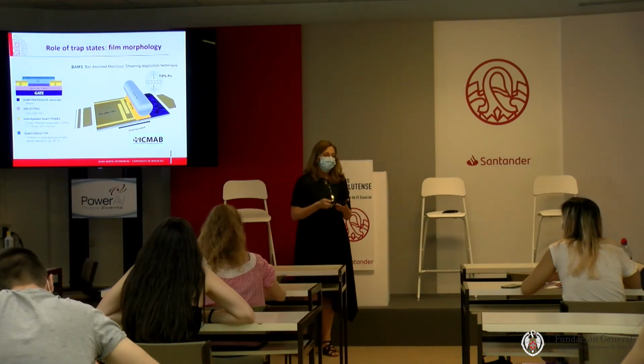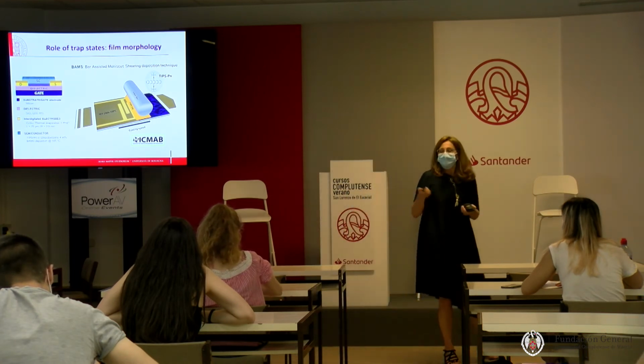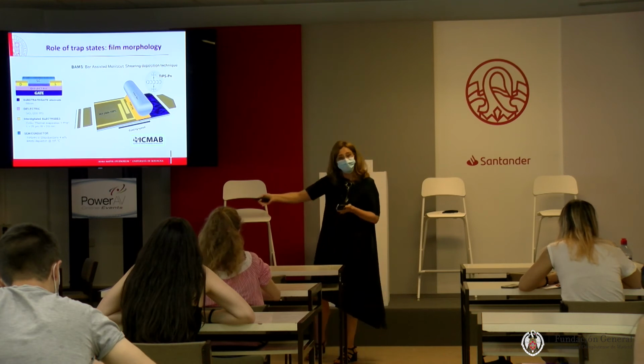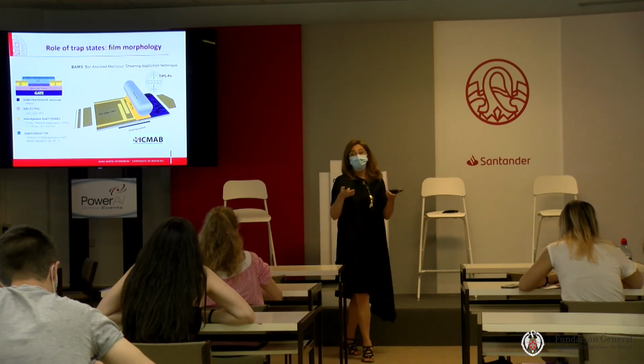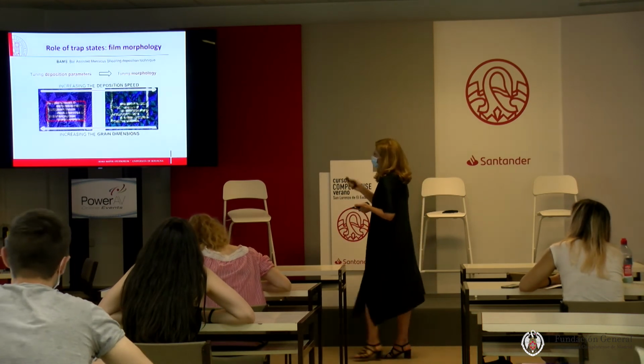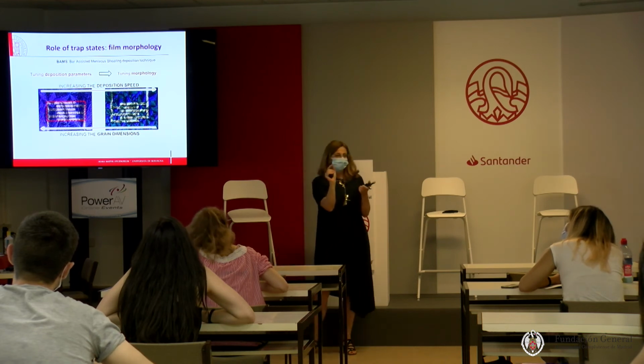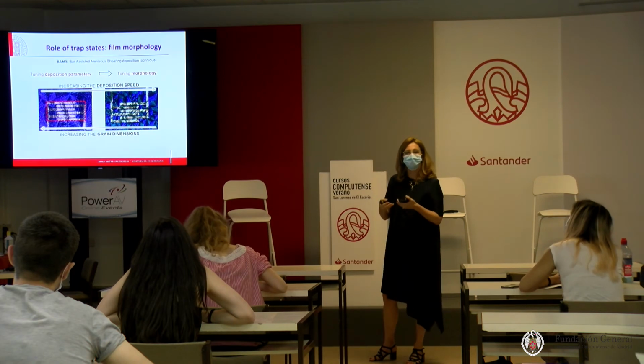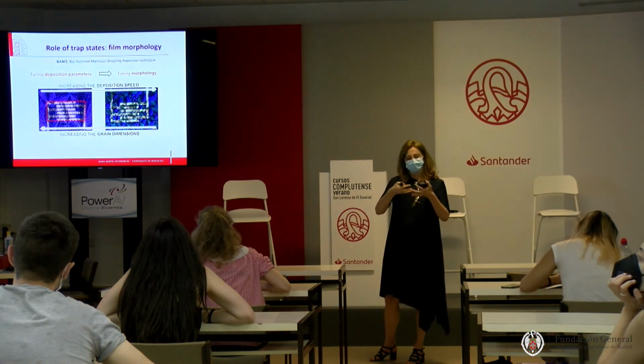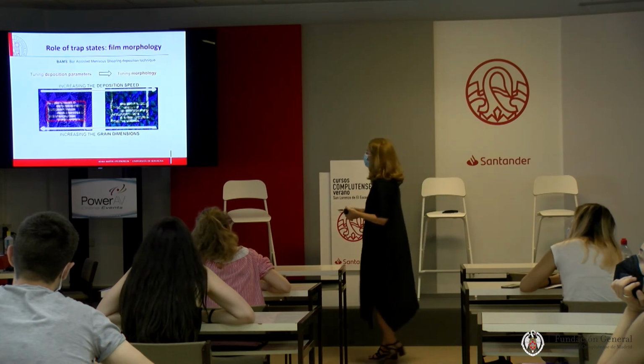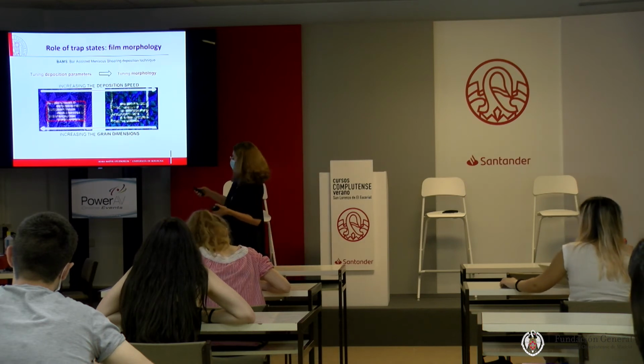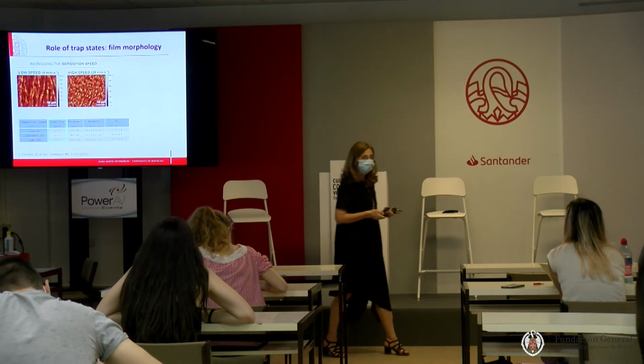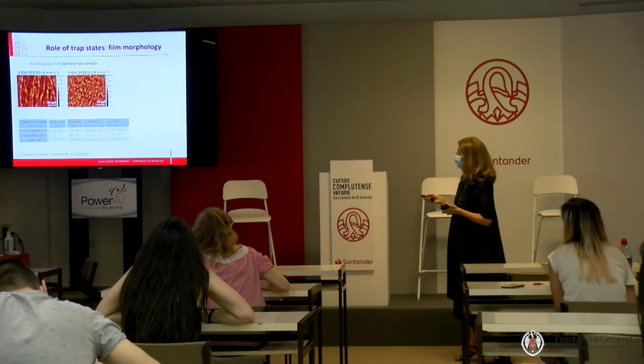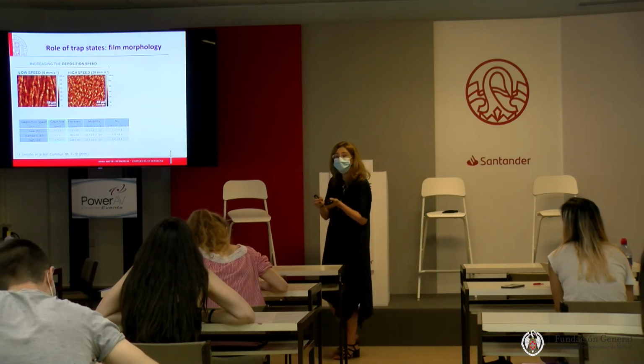What I really want to comment lastly is the role of defects that we can control by controlling the morphology of the thin film. Here I'm going to show you how, by controlling the speed of this solution deposited organic thin film, we can change the morphology of the grain of this polycrystalline film. You see clearly, these are two devices. The metal strips are the source and drain contacts. We call them interdigitated. You see, they're like fingers of two hands, one inside the other, deposited at two different speeds. You see that the grain shape and size is different. But you see it more clearly in this atomic force microscopy image. Then you see that by increasing the speed, we reduce the grain size.